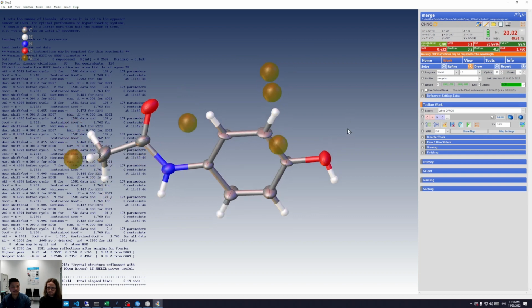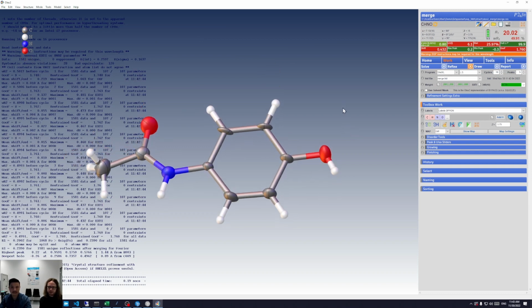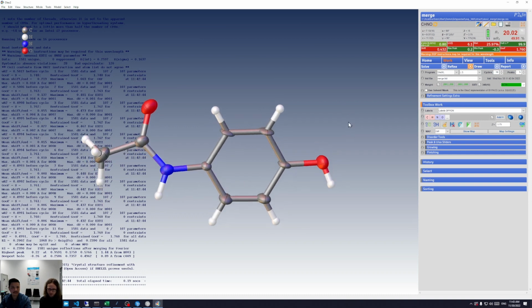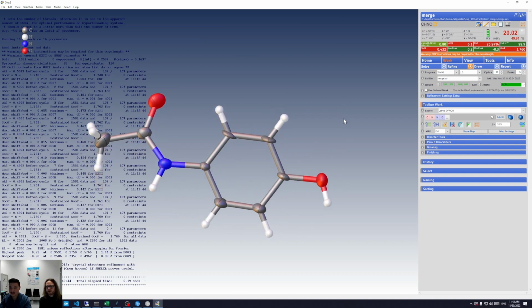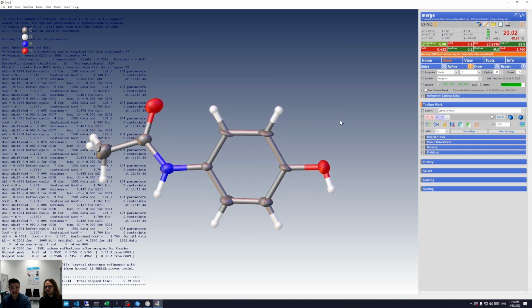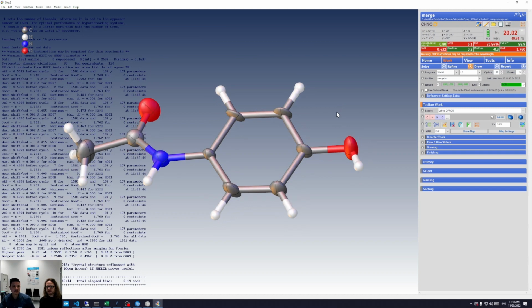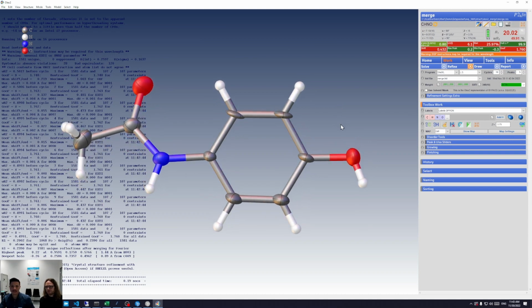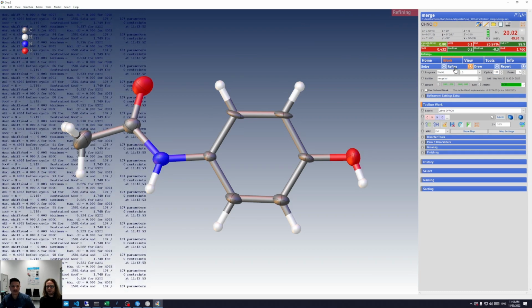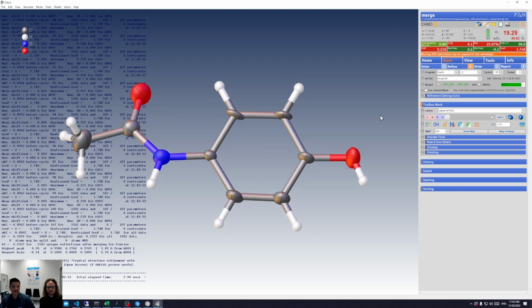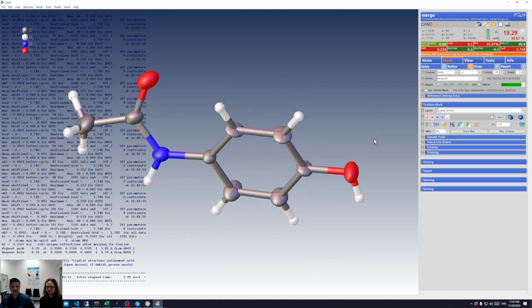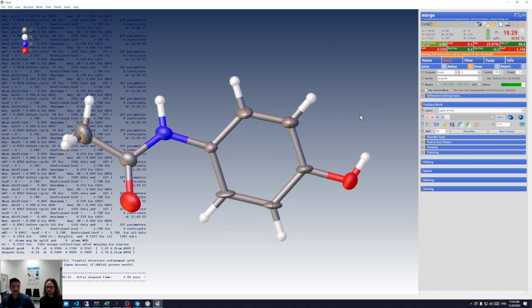They are higher, but this is not because the data quality is worse, but just because there are systematic inaccuracies of the modeling of the data, and experience shows that the quality of the structure is still very high, so it's much higher than what you would expect from an X-ray structure with similar metrics. It's just that we are, let's say, using metrics that are coming from the X-ray world, which are, strictly speaking, not quite the right ones for electrons. This is, let's say, still a bit evolving in the field, but the structure looks very, very good.